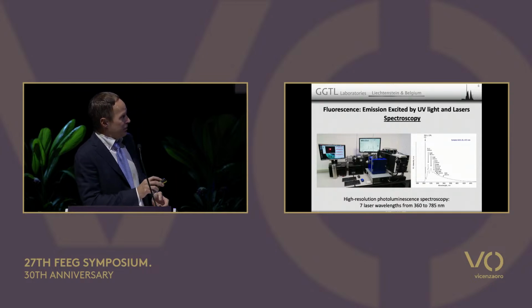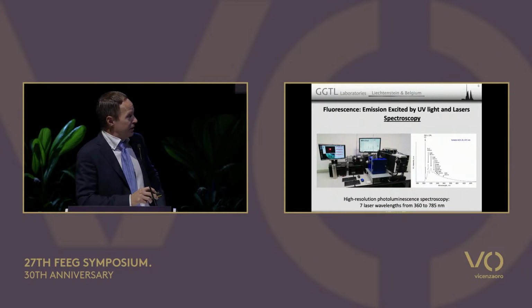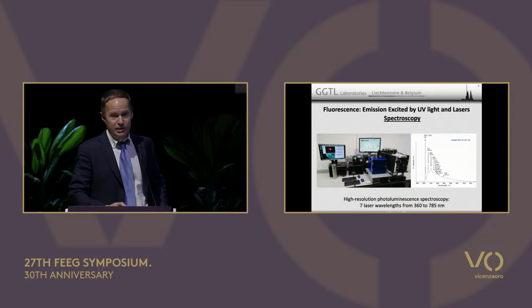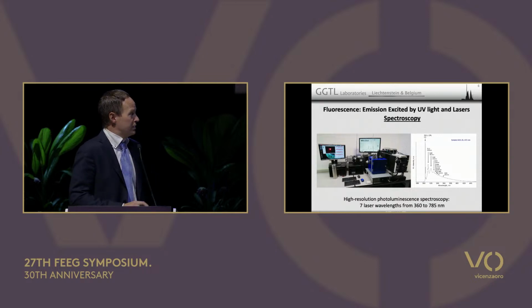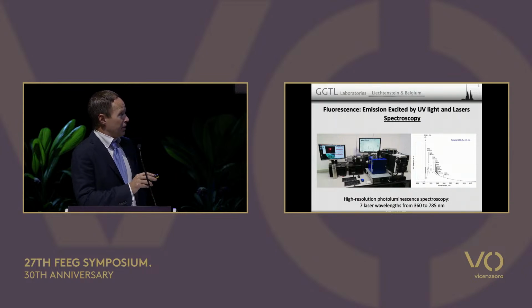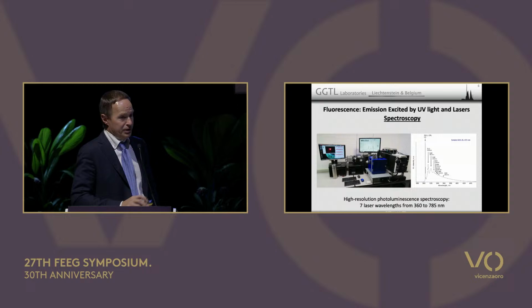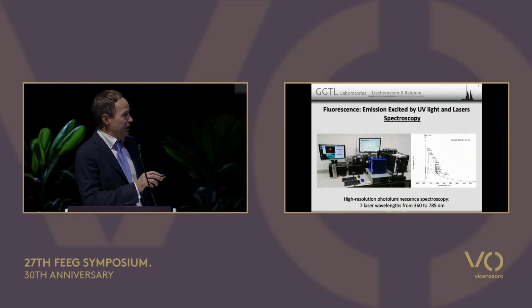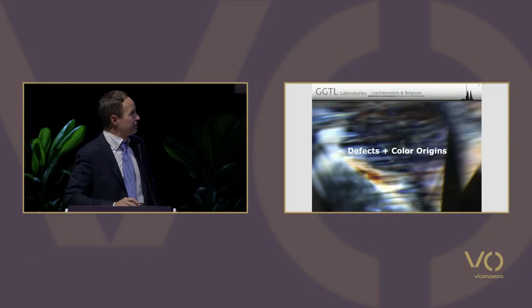This is a fluorescence spectrum. It shows you at what wavelength your stone emits. Since we're centered at about 520 nanometers, this correlates to green fluorescence. This is the H3 center. Typical structure in diamond: you have a zero phonon line, which is a purely electronic transition, and then you have the vibronic bands that all relate to the same defect. So this entire band that you see here is the H3 center, though oftentimes only the zero phonon line is noted and not the other ones.